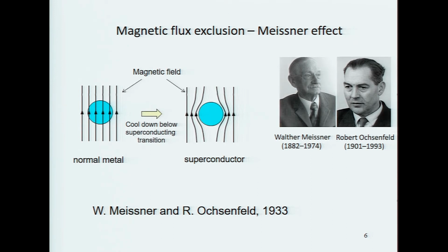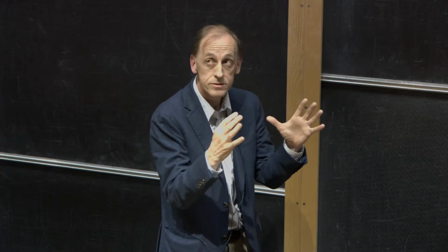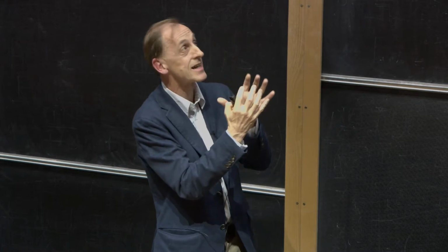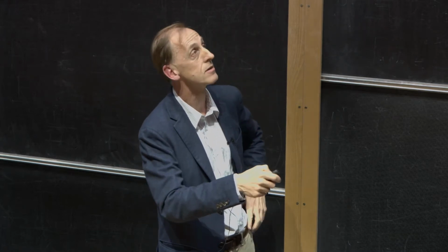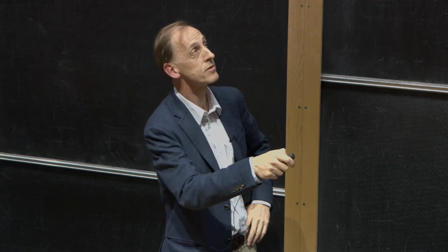But if you cool a superconductor down in a magnetic field, at high temperatures it's still just behaving like a metal. But at low temperatures, when it goes superconducting, remarkably what happens is that the superconducting material just excludes the flux and expels it actively from the interior of the metal. So literally the flux is pushed out of the metal like this.